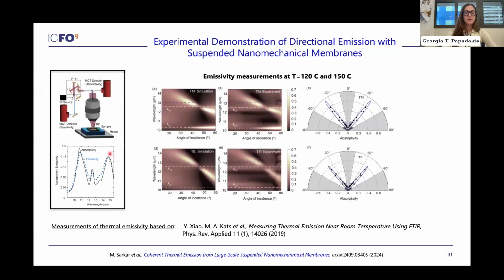So the first experiment we do is simply we put the device inside the microscope, and we do absorptivity measurements. And what these really are reflectivity measurements. So we really just measure reflectance, and we take 1 minus R, which is the absorption. And then we also put the material on top of the heating stage, we heat it up, and we get the emissivity, and of course they have to be equal due to Kirchhoff's law.